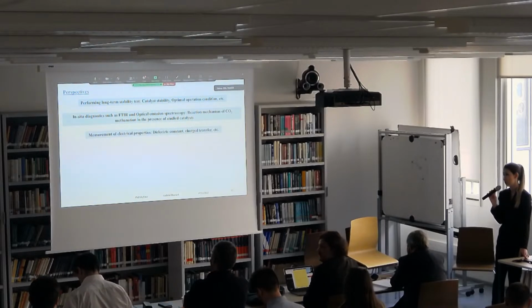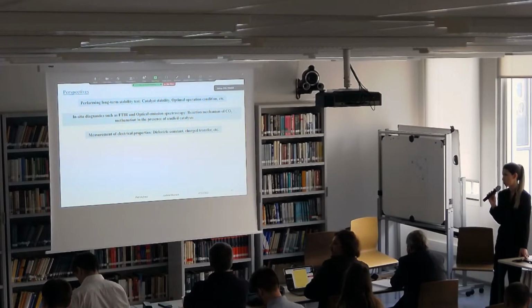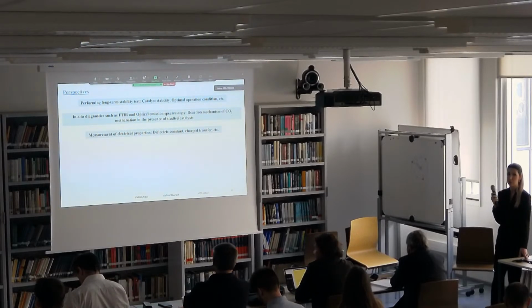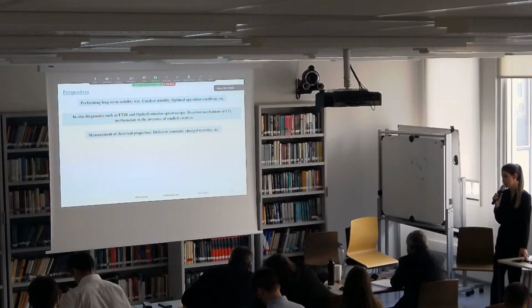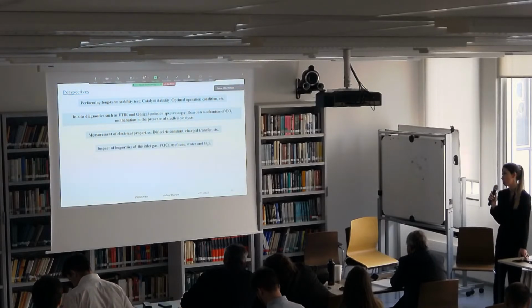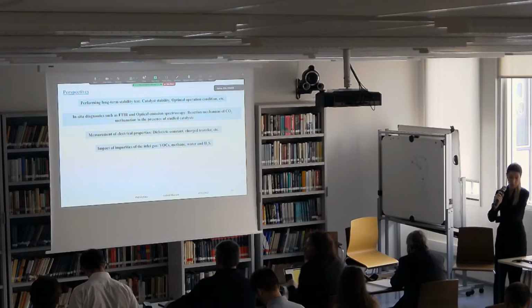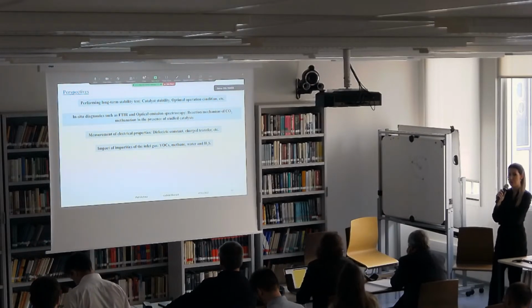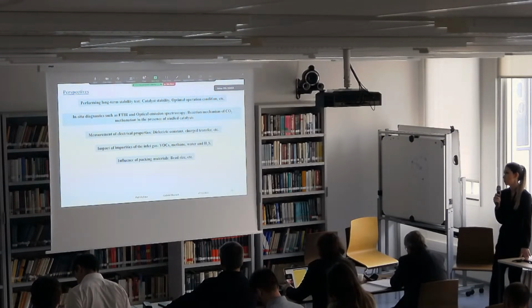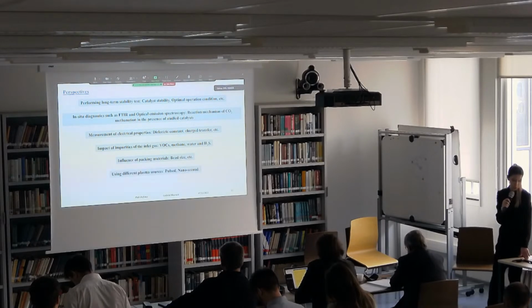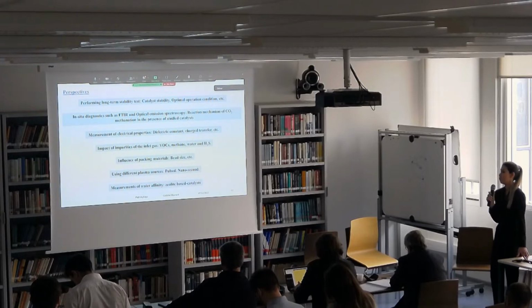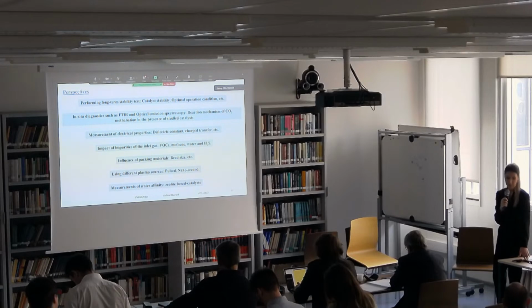As I already mentioned, there is another property which actually plays an important role, and there was no specific trend to justify the catalytic behavior. Dielectric constant could be a very important aspect in the plasma condition. Also, the study of the impact of impurities in inlet gases, because mostly in industry, CO2 comes from biodigesters, which always have impurities that can affect the catalyst activity. Also, the influence of packing materials such as bead size, which can affect the plasma properties for sure. And also using different plasma sources for this group of catalysts, and measurement of water affinity for measuring the basicity of the catalyst.